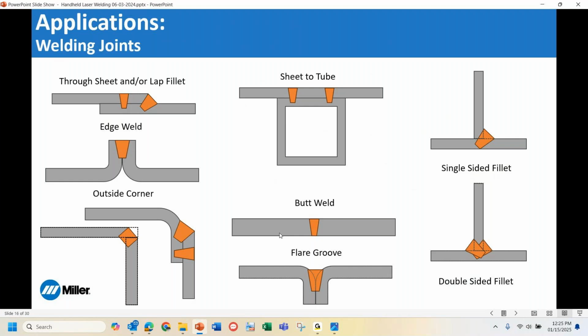And then if we look at the right-hand side, of course, a fillet weld, those are readily and easily accomplished with this process. And if you do a double-sided fillet weld, even though the external leg size is smaller, we can actually provide a significant amount of strength, because now we can penetrate into the component and get a lot of theoretical throat into the base of the material, versus having that external gusset that causes the distortion in those joint configurations.